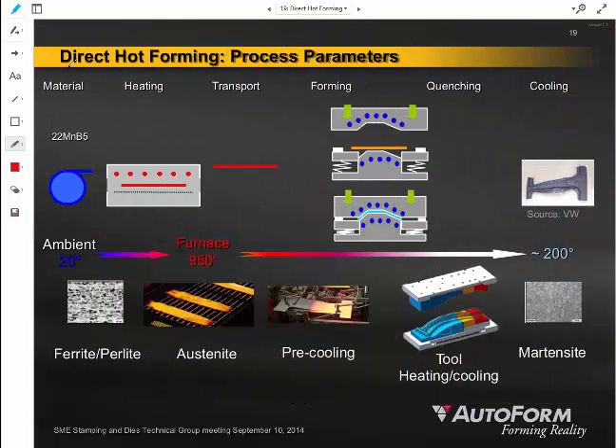So when we take this idea of the direct hot forming process, we take that boron steel, we take it from room temperature to 950 degrees C in the furnace, and that heats that material up to its austenitic microstructure, right? That's the relatively amorphous, not fully formed grains or crystal structure microstructure. We form it inside of the die, and you'll notice I have all these little blue circles inside my illustration. Each one of those represents a liquid-filled cooling channel. Right, so this die is going to be piped, and it's going to have fluids passing through that die trying to maintain a particular temperature.